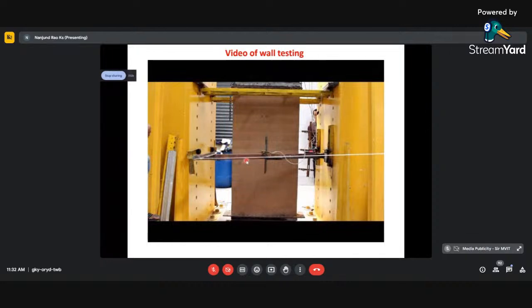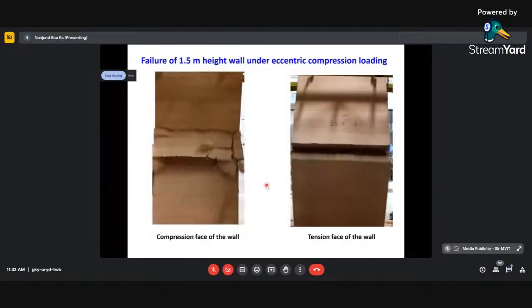Whenever you have a very large H/D ratio, the failure is not by material failure, but by slenderness effects, which is the bending that will take place. And that you can very clearly see on the opposite faces in the next specimen. This is the compression face, crushing that took place, and this was a tensile face. So it simply opened up along the compacted layer. So this is what happens when the slenderness ratio increases.